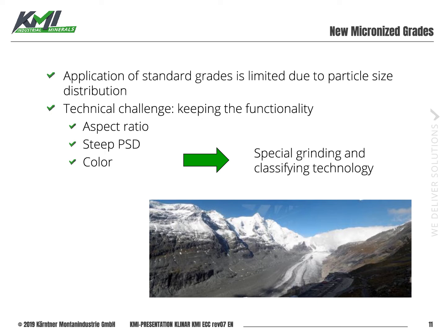That means keeping a high aspect ratio, also having a steep particle size distribution, to have most of the product in the so-called working window, and also to keep the color gray with a metallic sheen. And finally, we have been successful and we developed a series of new so-called micronized and sub-micronized micaceous iron oxide products.